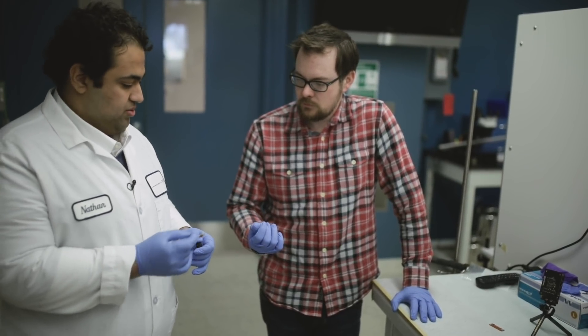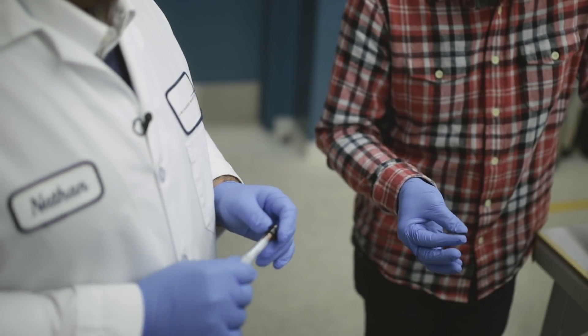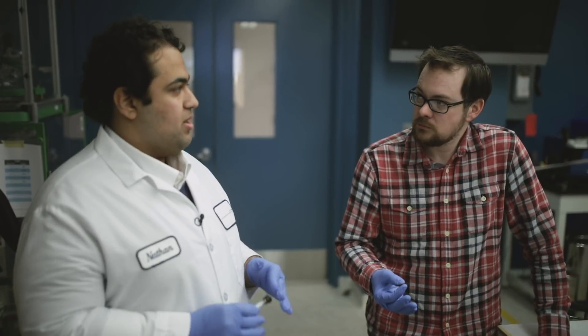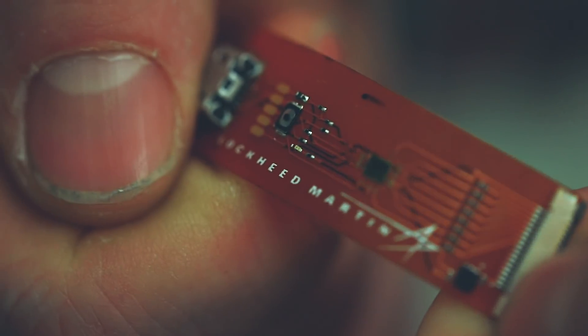What we have here is the nano copper paste — this is what would be the drop-in replacement for solder, although we have many other cool uses for it. I'll just put a little on your finger — if you spread it around and buff it a little, you'll see it maintains its shininess and looks just like copper, and it's spreadable like toothpaste. Our lab-scale process takes about four days per kilogram. Other applications involve additive manufacturing, printing electronics and antennas specifically. We've done work making flexible substrates — the chip right there, the connections to it were printed with nano copper, because regular solder is not ideal for flexible applications. Once the nano copper technology matured, Lockheed Martin decided to help start a spinoff company called Cuprion, which handles all of the consumer, non-space, non-defense marketing of the nano copper material.